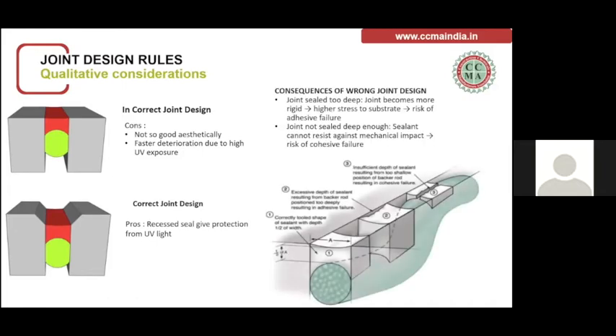The consequence of wrong joint design: if the sealant is too deep, then it becomes rigid and there would be high stress on the substrate and there would be adhesive failure. And in case the sealant is very shallow, then there is a chance of cohesive failure.